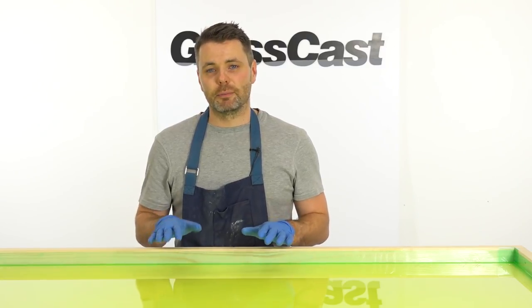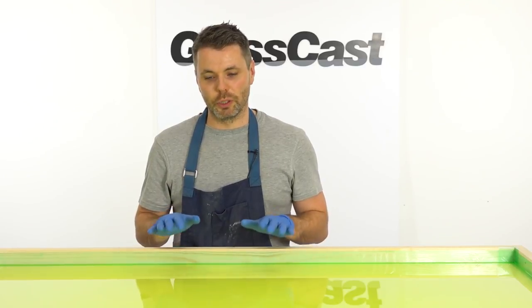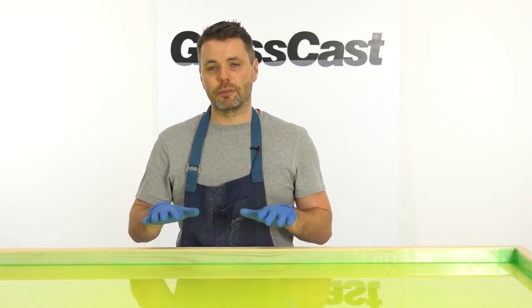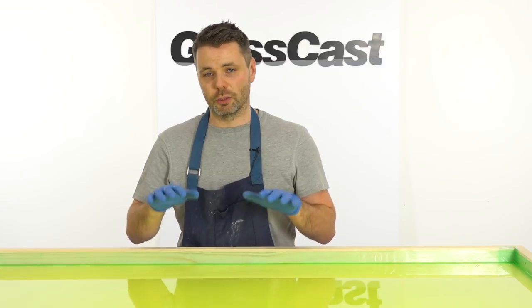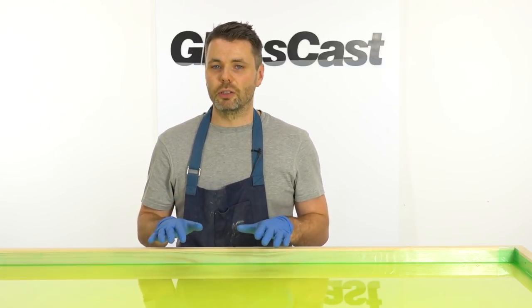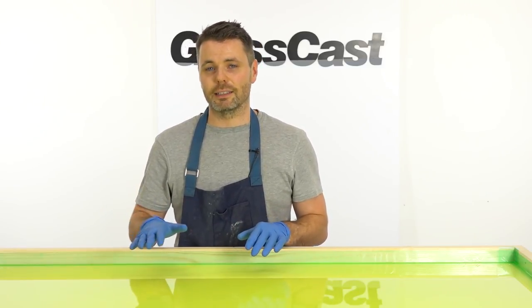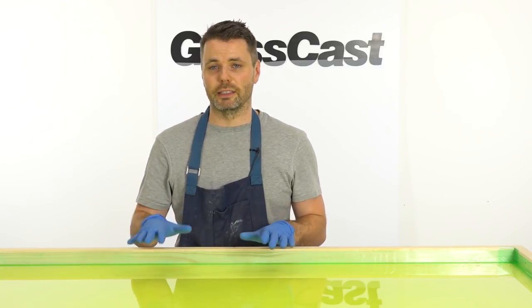I now need to leave this base layer to partially cure to what we call the B stage. That's where it's firm enough to support the weight of the planks without them sinking into it, but it's still got some tackiness that will allow the next layer of resin to bond perfectly to this one. In an ambient temperature of 20 degrees Celsius, this will take around 12 hours, so overnight is ideal. Whatever you do, don't just forget about it though, because the next layer of resin really needs to go down whilst this one's still tacky.